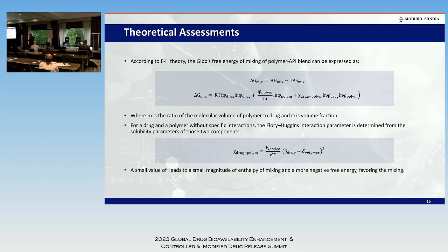Yes, and in that case, a certain polymer is being used, VA64, but that is because that polymer and those drugs are able to create that interaction to create a miscible pair. It's not just the Tg that helps them to stay there. It is also hydrogen bond interaction between PVP and those drugs.